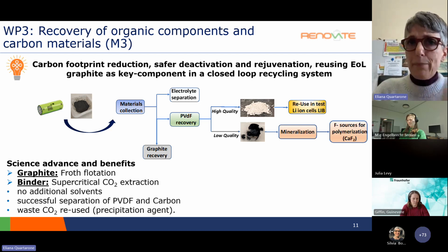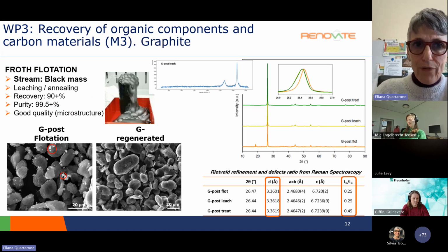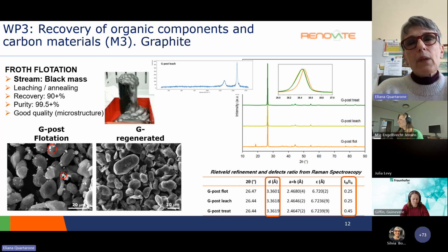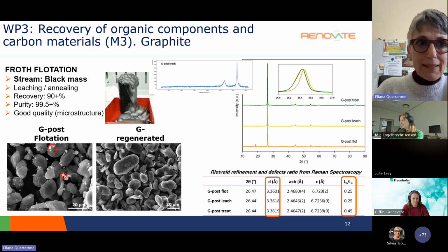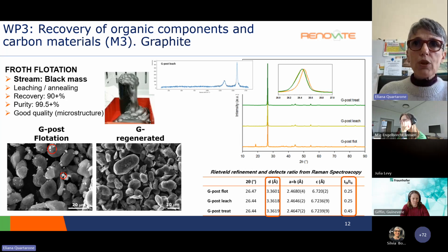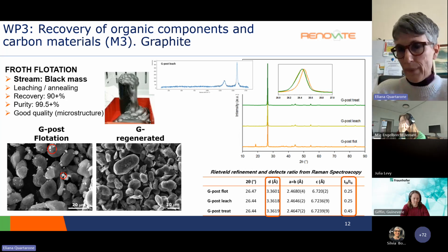This is just a first example of what we are doing to recover graphite by means of a greener froth flotation process, which means using greener frothers and collectors. And we are working on a real black mass coming from end-of-life batteries of electric buses. We are having very high recovery yields, higher than 90%, with a refining of the graphite very close to a potential battery grade, because we are now at a purity level exceeding 99.5%, with very good microstructure and also morphology that we are targeting by means of Raman spectroscopy, of course.